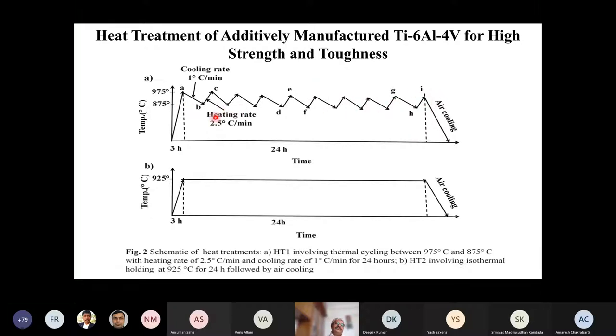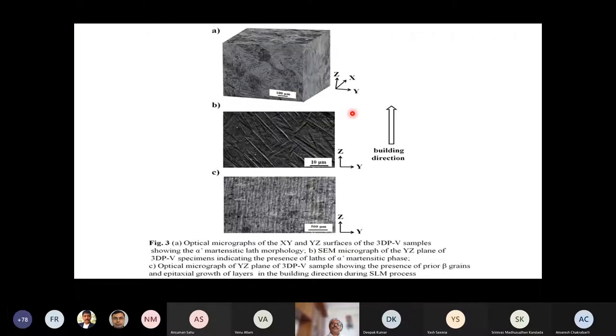And this was not out of some kind of intuition. We could examine the microstructure, and based on that, since it has a lamellar microstructure, we wanted to have a globular microstructure, which I will show you in the next slide, because that would give rise to the best results in this condition. And then we designed this strategy, and I will show you that we have got significant properties, and in fact this work was very highly appreciated in the international community, because no one has done this kind of optimization, just by heat treatment.